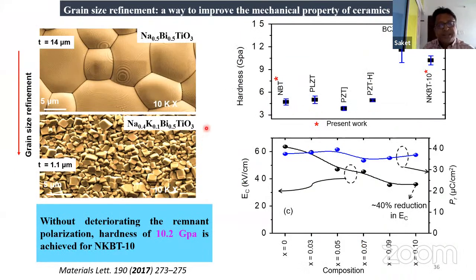So in that A site disorder, we put potassium in between, and you can see that the grain size is drastically reduced. Then we measured its hardness. It shows a good hardness value, 10.2 gigapascal, but lesser than BCZT. BCZT is barium, calcium, zirconium, titanate.